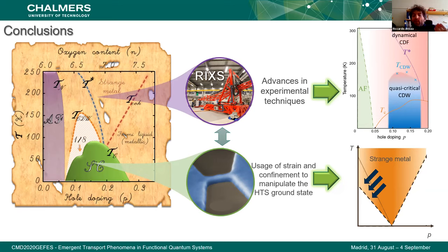And to check this evolution, what people have done is applying a magnetic field. And when applying a magnetic field, what you see is that the charge density wave becomes three-dimensional and really becomes a static phenomenon, which is really 3D, because it is not only related to the copper oxide planes, but is also connected to the cross-talk between the different copper oxide planes.